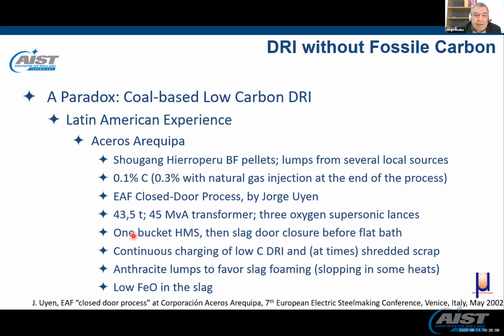In the case of Aceros Arequipa, the DRI was made of blast furnace pellets, curiously from Shougang, blast furnace pellets, not DRI pellets, and lumps from several local sources. It was also 0.1 carbon. A lot of R&D from their people to get higher carbon, testing natural gas injection at the end of the process, but it was very slow and somewhat expensive, so it was not practiced for a long time. They melted this low-carbon DRI with the so-called closed door process by Jorge Uyen, the steelmaking manager at that time.